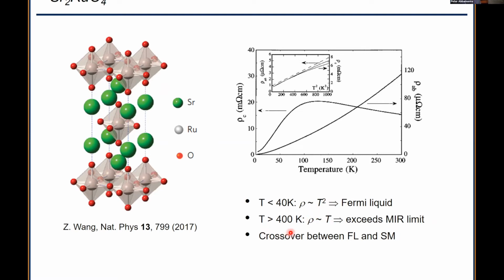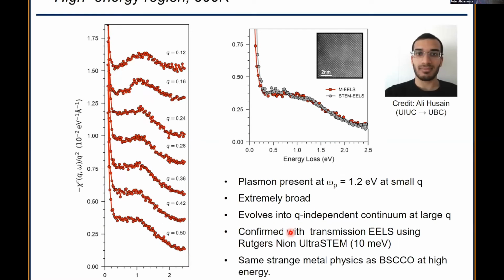But if you go above room temperature, eventually it becomes T linear and it surpasses the Mott-Ioffe-Regel limit and becomes a bad metal. So this is an interesting material that turns from a Fermi liquid into a strange metal as a function of energy scale, either through temperature or maybe the speed of the measurement and so on. So it's an opportunity to look at something that bridges conventional physics to strange metal physics like we've seen in BISCO. So if you look at high energy, this system looks a lot like a strange metal.